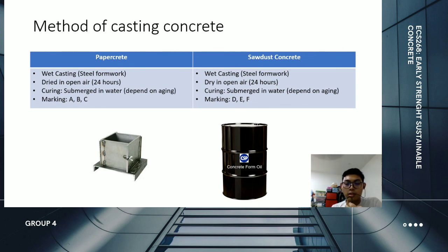And next, for the sawdust concrete, we also use wet casting and a steel formwork with the same concrete form oil to help when we open the steel formwork. And then for sawdust, we also dry it in open air for 24 hours. The same goes for curing, we submerge it in water depending on the age that we want before we do the compressive test. And then for marking, we use D, E, F, which is different from papercrete, so there is no risk of changing or confusing the concrete cubes.